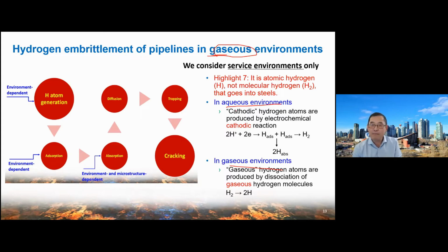A very important source for hydrogen production in the liquid phase is what? It is corrosion, right? During corrosion, hydrogen can be produced by cathodic reaction. H+ combined with an electron produces hydrogen. This hydrogen has two possibilities. One is hydrogen atoms combining together to become H2. This is a gas bubble, which will attach on the steel surface and cannot go into the steel. Another possibility is hydrogen ADS becoming ABS. So this is hydrogen that will embrittle the steel.